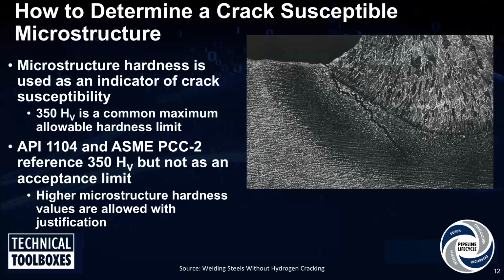So how do we know if we have a crack susceptible microstructure or not? Well, when you qualify welding procedures, you don't really go to evaluate the microstructure of a weld per se. But what you do is you measure the hardness. And the thinking there is crack susceptible microstructures tend to be very hard and very brittle. So if you have a weld heat affected zone that has a high hardness, you suspect that you have a high volume of that microstructure that is crack susceptible.